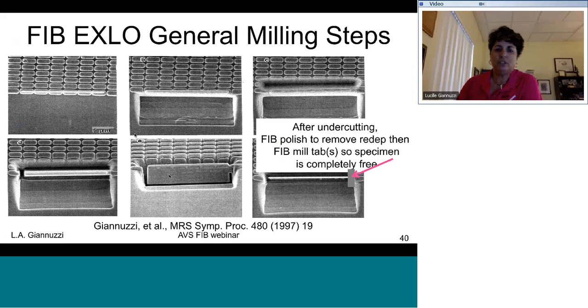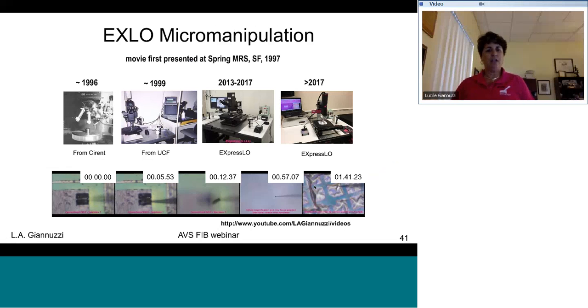So, in fact, if you go to the early literature, you'll just see reference to lift out. You won't see reference to ex situ lift out because there wasn't another technique. But this is very similar to what you would do with any 2D sample prep or even the start of in-situ lift out. So there's your sample, your deposition layer, trench in the front, trench in the back. Continue to make it thinner. You undercut the sample. In this case, there's only one little tab free. I like to do 2 tabs now. But after you tilt the sample back down, you thin either a portion or the entire sample to electron transparency. And then you cut the sample free such that you have a completely freestanding sample inside of the trench. And then you pull that out of the instrument.